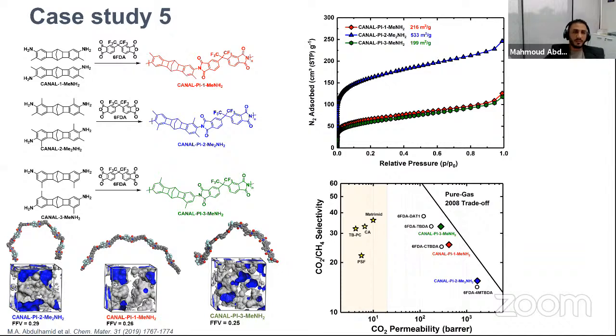Also, we have studied the effect of having methyl groups. Again, we go back to the structure-property relationship. What would happen if we have one methyl group next to this imide linkage, or two methyl groups next to the imide linkage, or even no methyl groups next to the imide linkage? We clearly see that the presence of methyl groups next to the imide linkage provides higher porosity and high BET surface area.